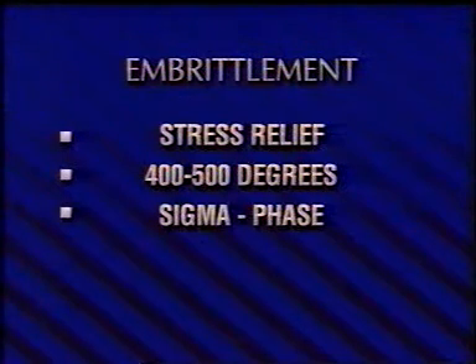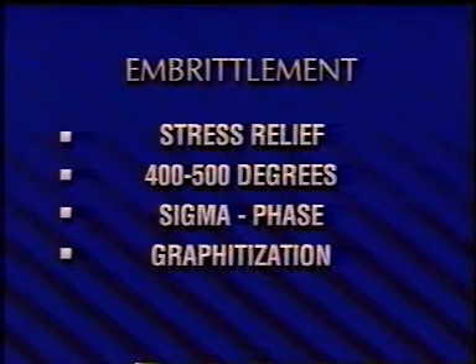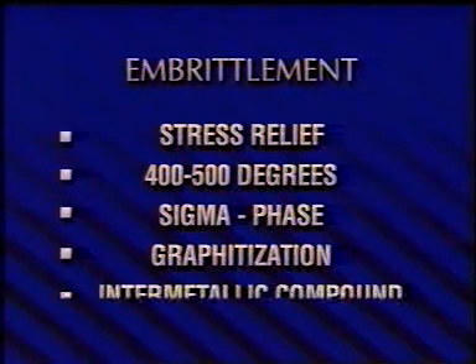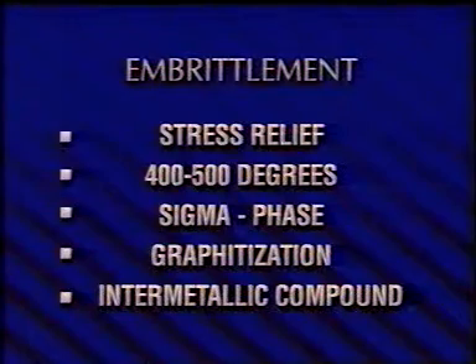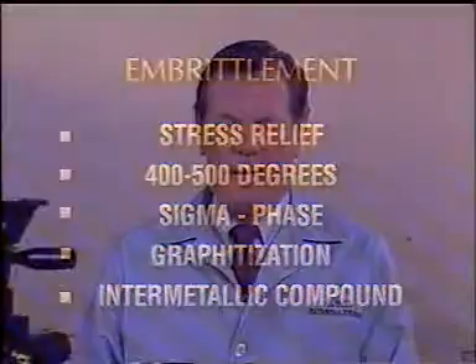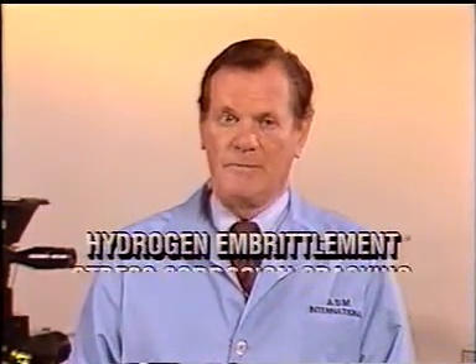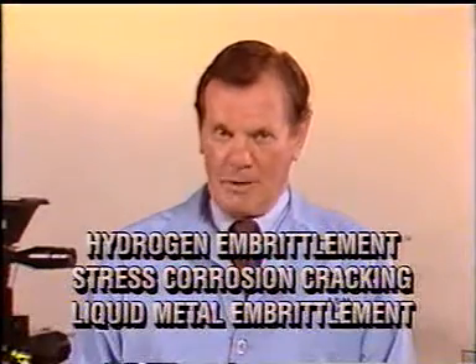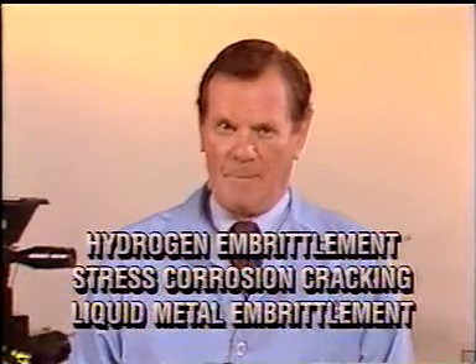400 to 500 degree embrittlement in ferritic stainless steels. 400 to 500, by the way, is centigrade. In Fahrenheit, the embrittlement occurs between 750 and 930 degrees. Sigma phase embrittlement in high chromium steels. Graphitization in carbon and low-alloy steel high-temperature piping. And intermetallic compound embrittlement in galvanized steel. In addition, steels and other metals and alloys can be embrittled by environmental conditions. Most prevalent are hydrogen embrittlement, stress corrosion cracking, and liquid metal embrittlement, which will be discussed in another program.